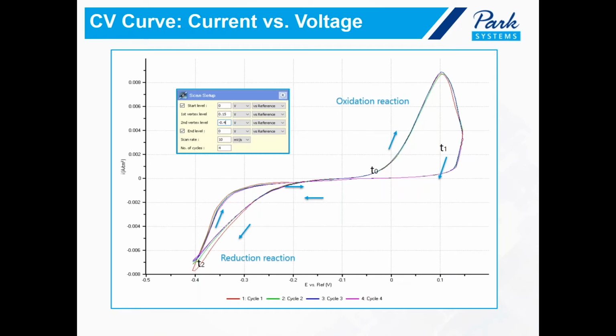This figure just shows you the CV curve that we obtained during cyclic voltammetry. We ran 4 complete cycles of the oxidation and reduction process, or redox process. Here you can see the CV curves that we have collected are quite overlapping to one another. If you analyze the results, you will realize that the redox processes are reversible depending on the amount of potential applied on the solution.